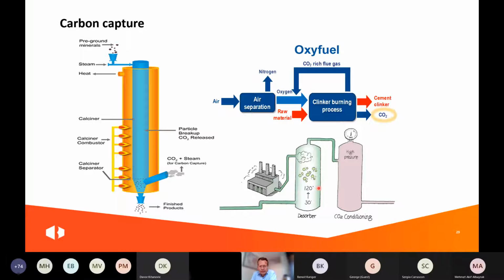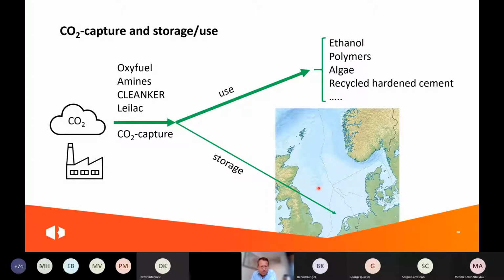There are more examples. You can do the same as with amine solution with lime itself by capturing CO2 around 600 degrees with calcium oxide and then heating it up to 1000 degrees and keep looping the calcium, capturing and releasing the CO2. Then of course, what are you going to do with the CO2? Well, there is sufficient capacity for storage in nearby empty gas fields for hundreds of years, actually, not only for the cement industry, but for all large emitters. But of course, we want to end up with the use of CO2 to produce ethanol or polymers or algae, that's already tried, but also to activate recycled hardened concrete.